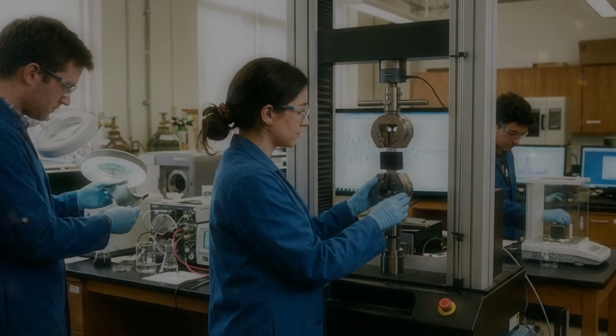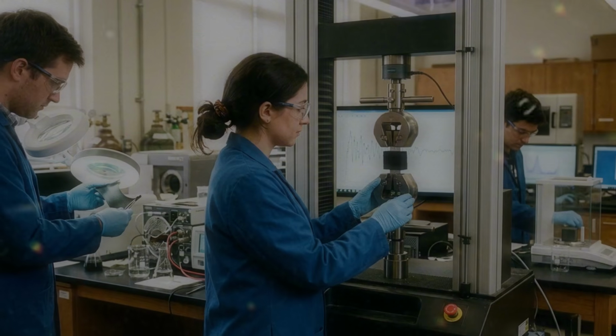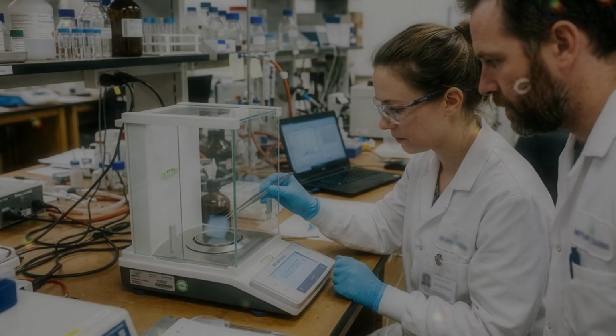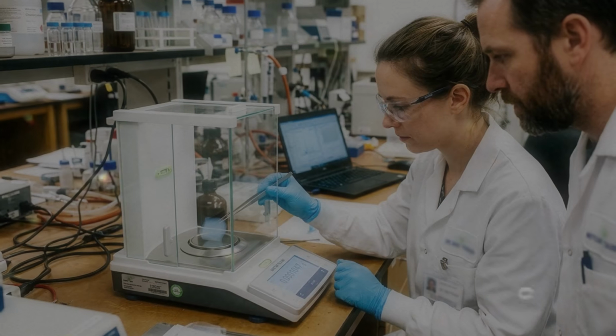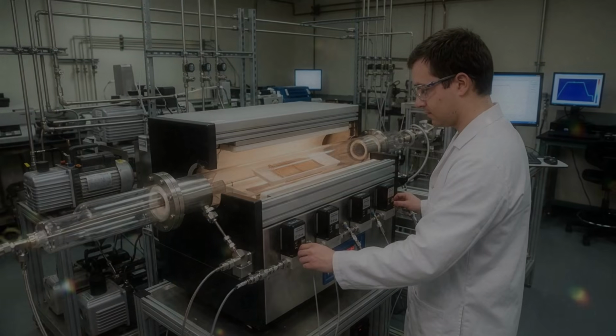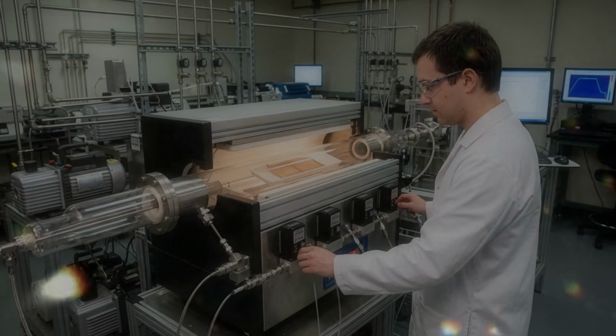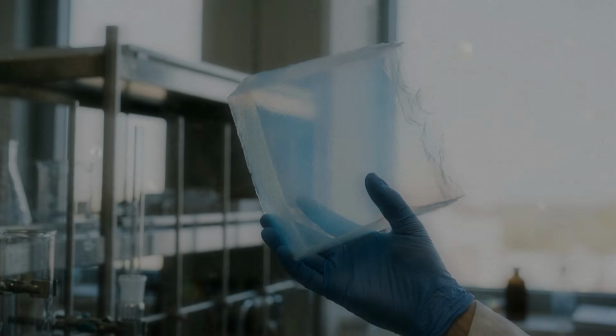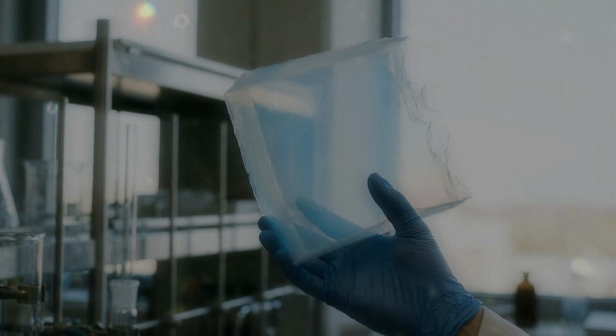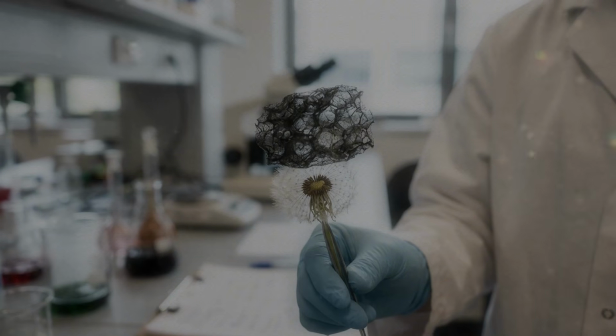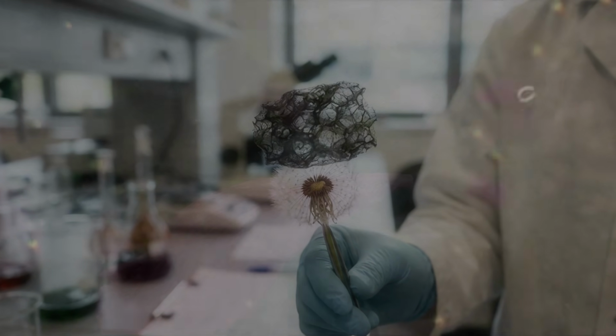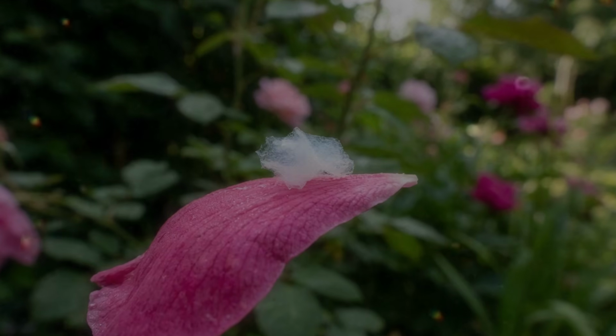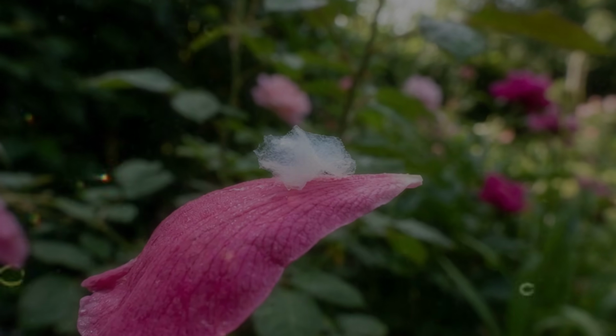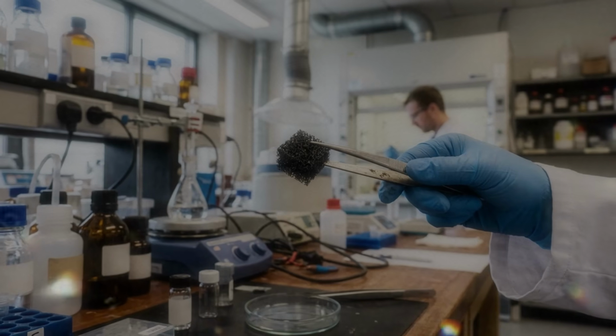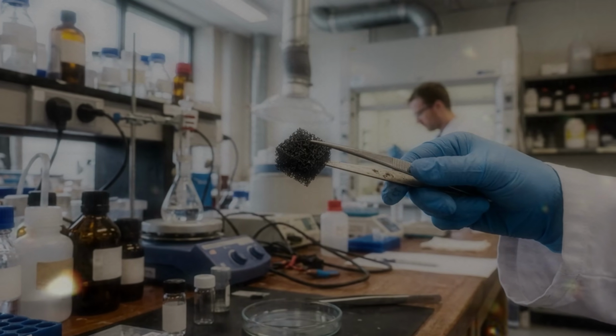The finished aerogel may also require surface treatment, cutting, coating, or shaping. Some pieces are machined carefully with specialised tools. Others are formed directly in their final shape because later cutting would create too much damage. Dust can be removed, surfaces can be sealed, and additional materials can be added inside the pores. A catalyst might be deposited throughout the network. A water-repelling coating might protect the aerogel from humidity. Conductive particles could improve electrical performance. A flexible polymer could strengthen fragile branches. In this way, drying is not always the final manufacturing step. It is the moment when the open structure becomes available for further design.